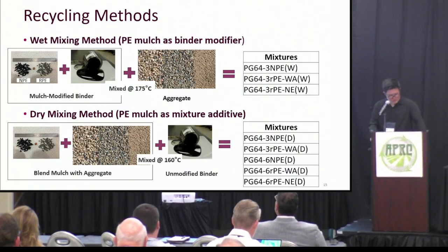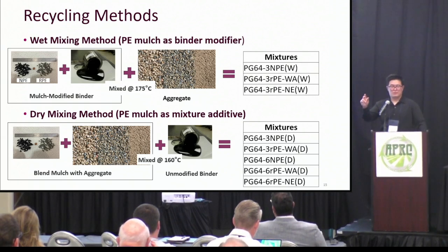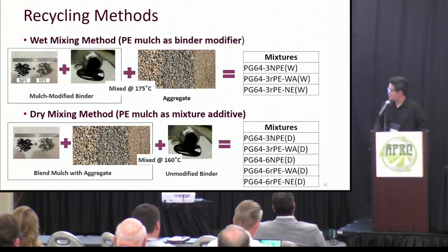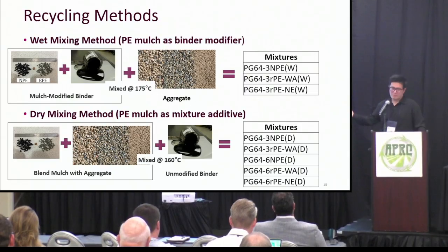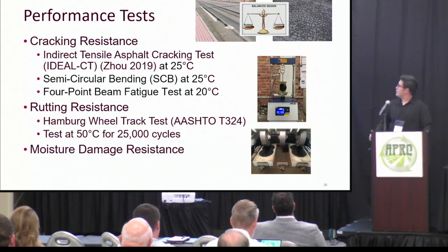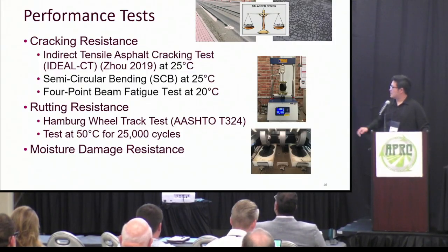So we evaluate both recycling methods. One is the wet mix method and the other is the dry mix method. For the wet mix method, we modify the binder first with the plastic, and then we add the modified asphalt into the aggregate. For the dry mix method, we blend the plastic mulch with the aggregate first and add the very hot unmodified asphalt. And we perform very comprehensive tests, for example, the cracking test, the rutting resistance test, and the moisture damage resistance test.